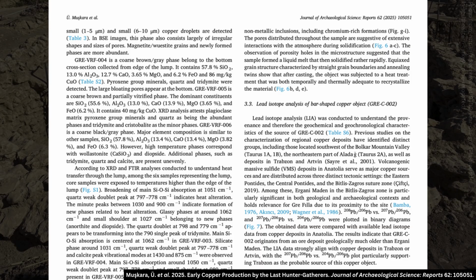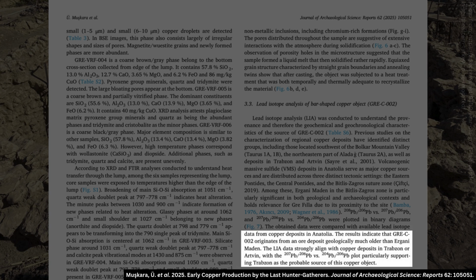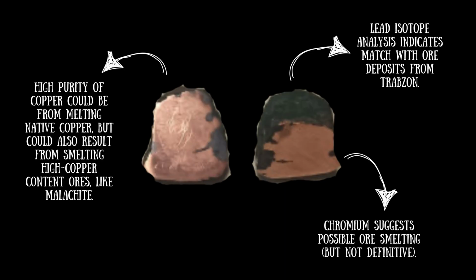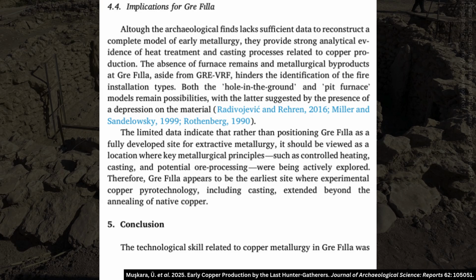It's also worth noting that lead isotope analysis, performed to determine the geographical source of the copper, showed that the bar-shaped object matched ore deposits in Trabzon. So there's some evidence to suggest that the copper originated from an ore, but the high purity renders it difficult to confirm for sure. The researchers are cautious about how they interpret their findings, and more work is needed to confirm the possibility that Gre Fılla's inhabitants started smelting copper ore sometime between 8800 and 7500 BC.